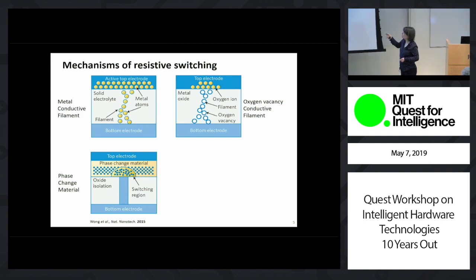Similarly, in insulating metal oxides, you can electrochemically activate oxygen to move into a top electrode or into a metal electrode from the oxide. And this could be areal or also locally filamentary. And oxygen vacancies are left behind, which have electronic states that dope the oxide and can give rise to local conducting channels as well.